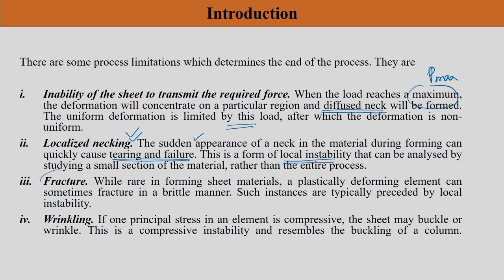So, that is what you quantify — fracture. How do you quantify necking? All these things will have some theoretical basis, and that is what we are going to see. Other than this, you are going to have something called wrinkling. In a deep drawn cup, you will see that wrinkling is going to happen on the flange region, and that could be because of the compressive nature of one of the principal stresses. It is like buckling of a column. Similarly, you are going to have wrinkling of the sheet away from its own plane — that waviness could be because of this.